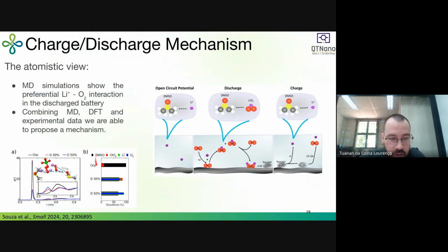If we look here at the occurrence of contacts between lithium and the species in the electrolyte, we see that in the charged battery, we see a lot of interactions between DMSO and lithium. When we go to the discharged, these interactions of DMSO and lithium decrease, and we see an increase between the perchlorate and the lithium, and the oxygen and the lithium. And with more and more discharge, this behavior continues. So combining the operando Raman, the DFT, and the MD simulations, we were able to propose a mechanism to understand the reversibility of our electrolytes.